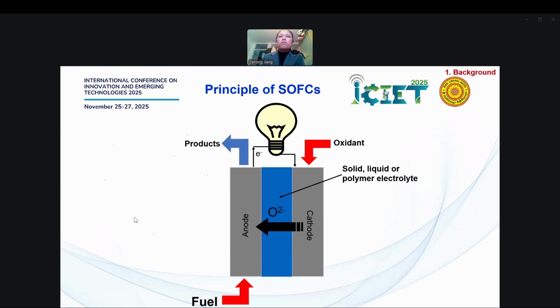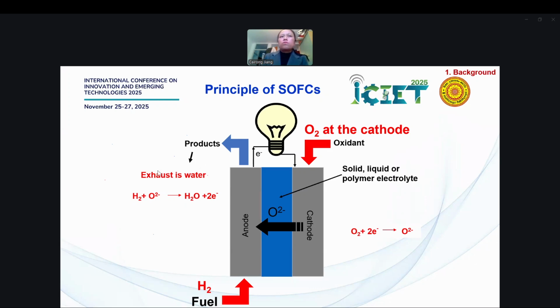The principle of a solid oxide fuel cell is slightly different from other types of fuel cells because they use an oxygen ion conductor as the electrolyte in the middle, the blue color as shown here. At the anode, we use hydrogen as a fuel, and the cathode is still oxygen, but the reaction mechanism is slightly different. At the cathode, oxygen is reduced into oxygen ions, and the oxygen ions transfer through the electrolyte and reach the interface between the anode and the electrolyte, and react with hydrogen to produce water and electrons. So this is how the light can be lighted. We get current this way, and of course water is the only exhaust if we use hydrogen as a fuel.